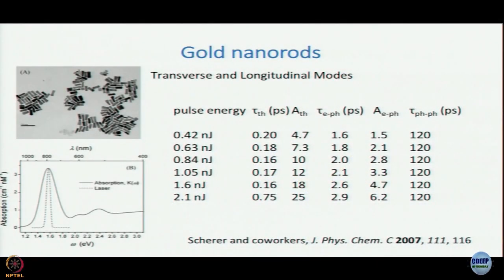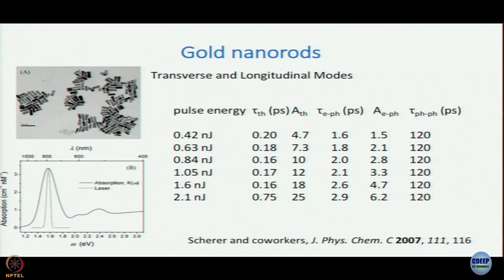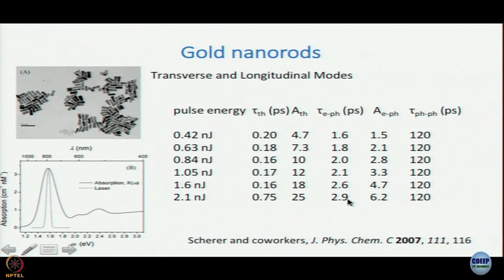So it is a more complicated experiment than simple pump-probe, but the time constants they obtained were: first, thermalization (electron-electron interaction) — the time constant went from 200 femtoseconds up to 750 femtoseconds as pulse energy went up, and the amplitude went up as well. Electron-phonon coupling time constant goes from 1.6 picoseconds to 2.9 picoseconds, and phonon-phonon coupling is not affected — it remains 120 picoseconds throughout.